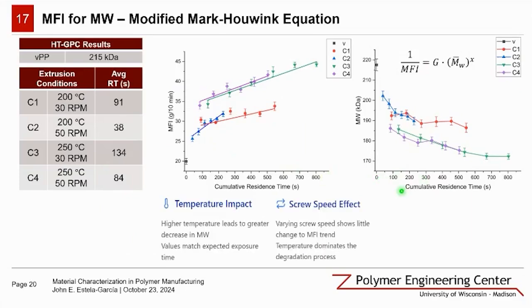Notably, higher temperature conditions exhibit similar behavior. We can see that by how the purple and green lines and the blue and red lines start having similar behavior. More notably on our data over here on the right, showcasing the molecular weight changes. So this suggests that temperature is a dominant factor in polypropylene degradation during extrusion.